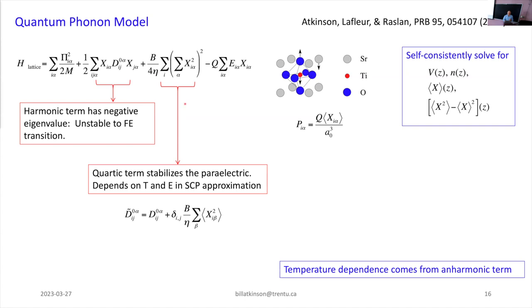And so you can do a mean field decomposition. I have four powers of the displacement operator here. So two of them show up as just an expectation value. This is actually a fluctuation term because it's expectation of x squared. And then the other two just remain as operators. And all I'm doing here is renormalizing my D matrix so that it now no longer has negative eigenvalues. So this is not a trivial renormalization because this x squared term is a function of position in my substrate. So it's possible to have localized states in my substrate from this Hamiltonian.